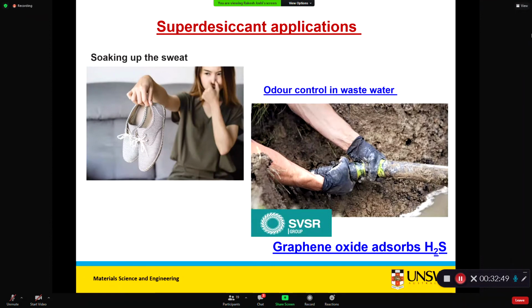And because graphene oxide absorbs moisture, we did some experiments with the industry partner SVSR. Can it absorb H2S gas? We didn't publish these results because this was an industry project, and we found that graphene oxide had a very good absorption for H2S in addition to H2O molecules. So it has two applications now: a desiccant for moisture absorption, and H2S absorption for sewer applications.